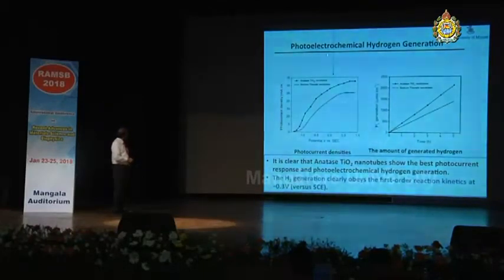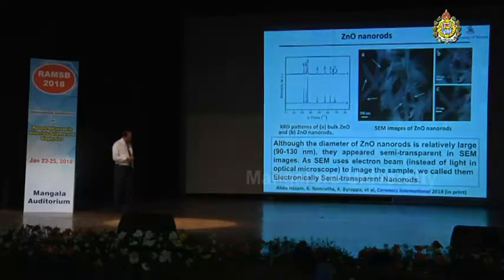And here we have carried out the photoelectrochemical hydrogen generation using these titania nanotubes, and the photocurrent densities are shown here, and the amount of hydrogen generated is shown in this graph. As you could see, it becomes very clear that titania nanotubes of anatase phase show the best photocurrent response and photoelectrochemical hydrogen generation. And also the hydrogen generation clearly obeys first order reaction kinetics at about -0.3 volts. Well, this is the zinc oxide nanorod work.